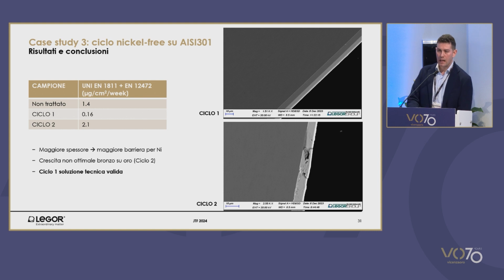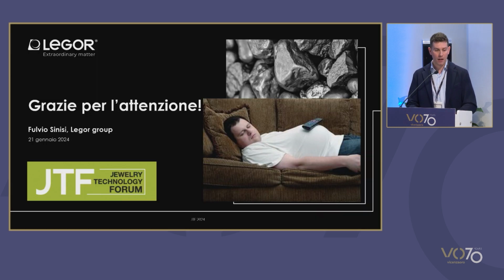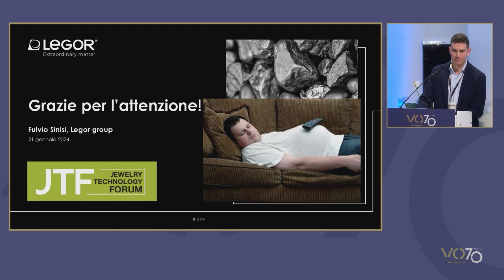There was too thick a deposit. Probably the deposit was not correctly carried out after bronze. Probably there is a lack of compatibility in having white bronze on top of a gold plating that was fully acidic. Cycle 1 provided us with a good solution, and over the next few weeks, a beta test is going to be performed using, again, cycle 1. My presentation is over. Thank you very much for your kind attention.